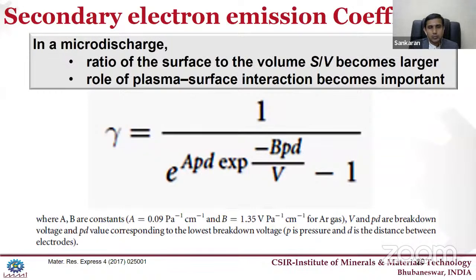The first thing we should know when talking about the microplasma cathode material is the secondary electron emission coefficient of a cathode material. In a micro discharge, the ratio of the surface to the volume becomes larger, so the role of the plasma surface interaction is very important. That parameter is the secondary electron emission coefficient, which depends on the pressure, the distance between the anode and the cathode, and the supplied voltage.